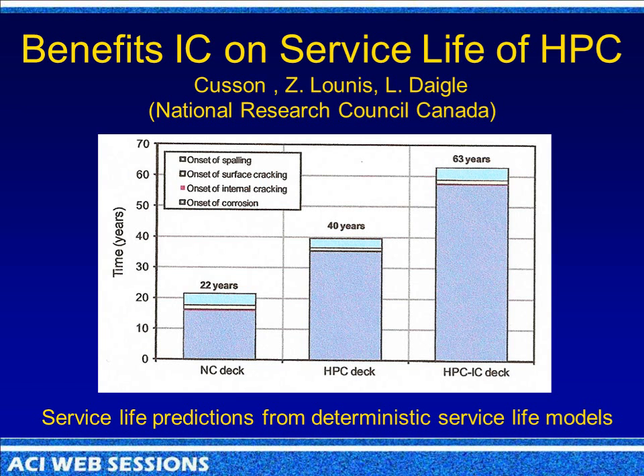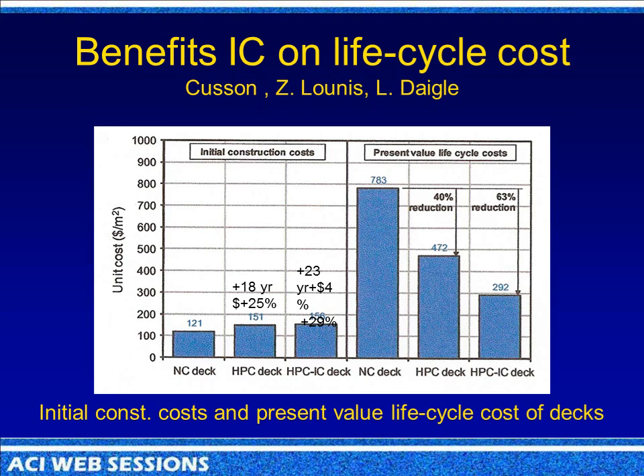Now look at the benefits here. These are life cycle models. This is normal weight, high-performance concrete. You get 40 years. You jumped 18 years from here to here. Just taking that same high-performance mix, adding internal curing, you jumped an additional 23 years. That's staggering. Here's the cost of these, initial cost. Okay, the high-performance mix was 25% more, and you added 18 years. The internal curing one, the cost was 29% more than the original, or 4% more than this high-performance, and you added an additional 23. You look at the present value of this thing, look at here, the benefit is unbelievable. 63% reduction just by adding internal curing.